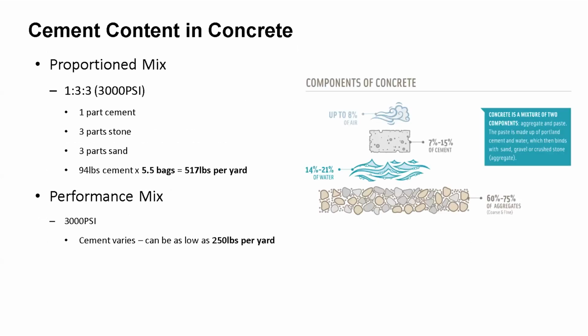That proportion mix that I was talking about, this is like a standard one. Historically, you might see a 1-3-3 mix, which corresponded to about a 3,000 PSI concrete. And it would be 1 part cement, 3 parts stone, 3 parts sand. And that mix would have been about 517 pounds of cement in it. The same mix, depending on where you are in the country today, with different admixtures and varying the rock, the size of the aggregates, etc., could be 3,000 PSI strength, but have only 250 pounds per yard, or around that. So we're making a lot of progress in concrete, thankfully.